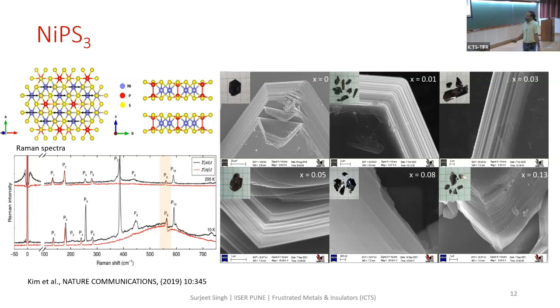Here I'm showing you some Raman spectra from this paper. Just to mention in passing that there are some very interesting things happening. So this is the Raman spectra at room temperature under 2 different orientations and polarizations. And this is the Raman spectra in the magnetically ordered phase. And you see this huge background which is appearing here. This is actually due to 2 magnon scattering. And these phonons, for instance, P9 here, couple very strongly with this magnetic 2 magnon continuum. And this leads to this characteristic asymmetry of the phonon line shape. And this can only be modeled by the Fano line shape because that describes the coupling of phonons with a continuum. So we have been studying all these in these zinc-doped materials.